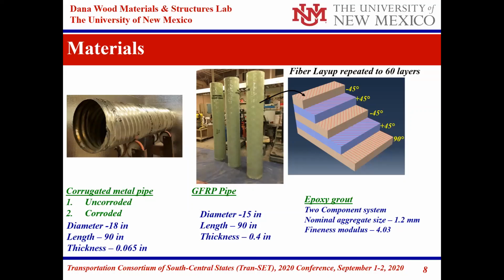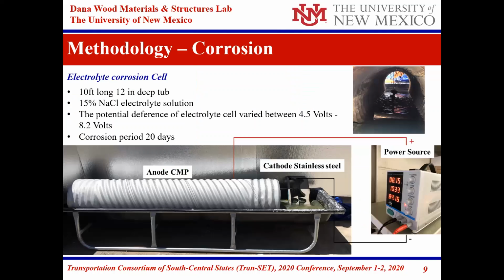So one of the things to do in our method is to simulate or mimic the corrosion that is happening in the pipe so that we can test both uncorroded and corroded pipe. So we created a corrosion cell that is basically, as you can see here, a corrosion bath that includes the sodium chloride electrolyte solution, with a potential difference to achieve corrosion in the pipe using a power source, as you see in the schematic, with a cathodic steel plate.